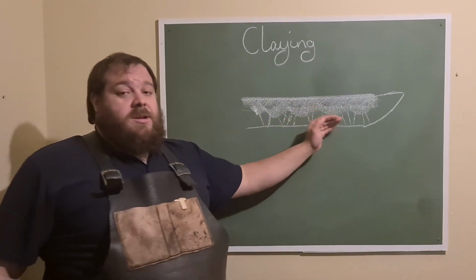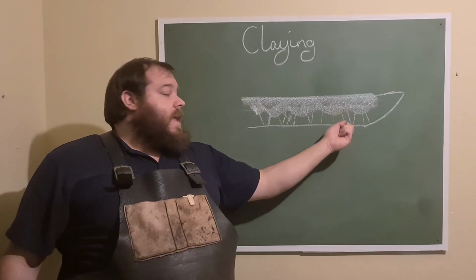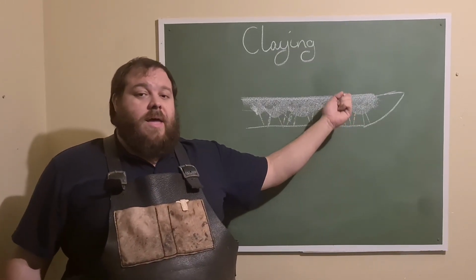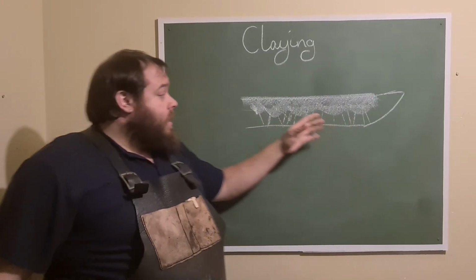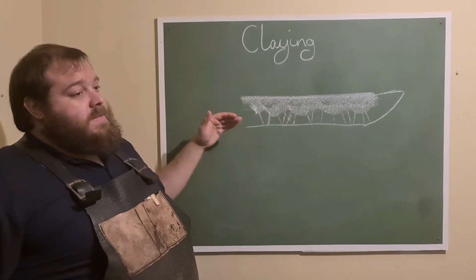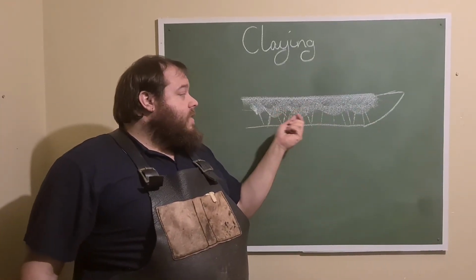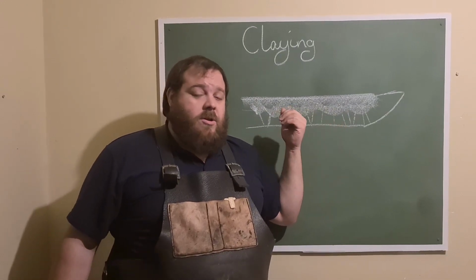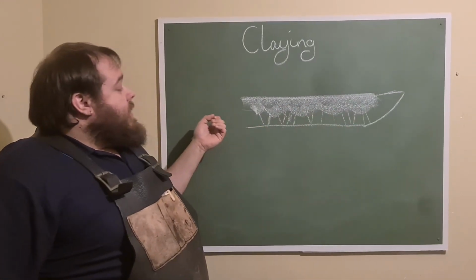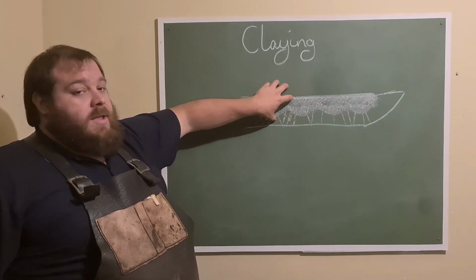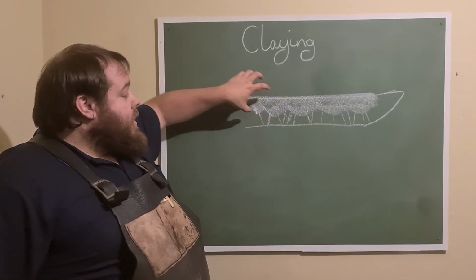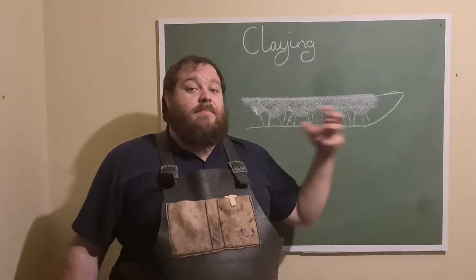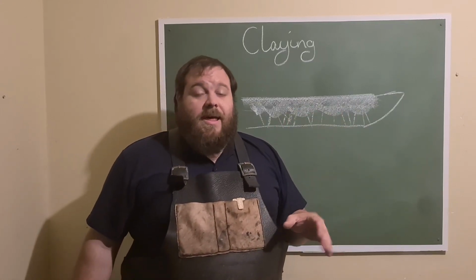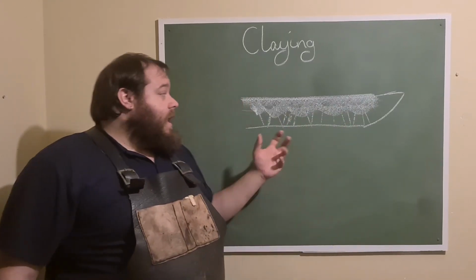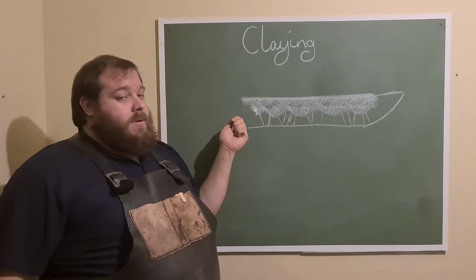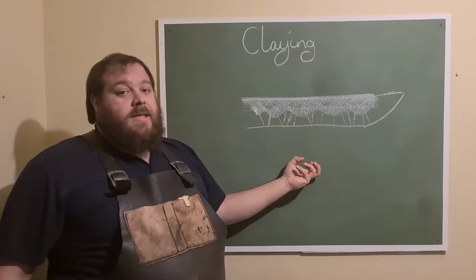The main thing about the ashi is that they are trying to draw just a little bit of that Hamon down into the edge. They are trying to draw that pearlite down into your martensite. And that is achieved by having these nice thin lines. And the reason that you don't have to match this on both sides exactly is because these are incidental amounts of clay. They're not huge amounts of clay. Now, with the main clay, obviously, given that it is the main thermal mass, it has to match. And if you match the ashi, then you're going to get a better ashi than you would if they were just kind of haphazardly placed. But either way, you'll get a better ashi if you have a nice hard line Hamon that is then able to bleed into those clay lines.